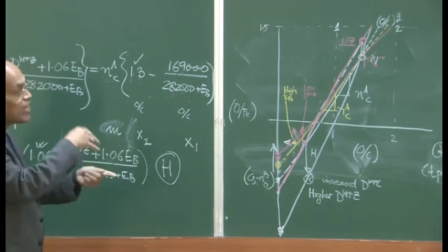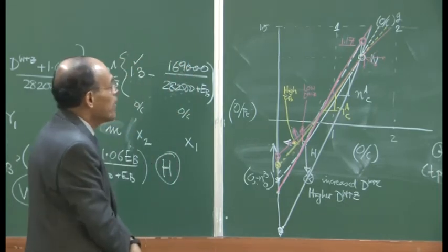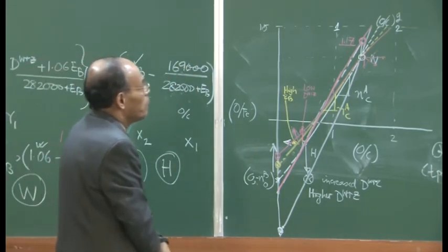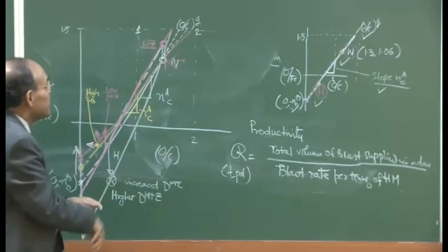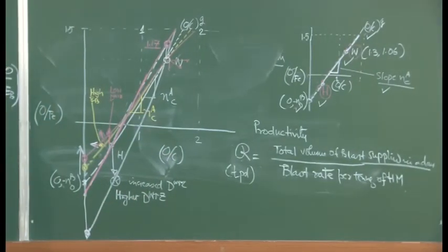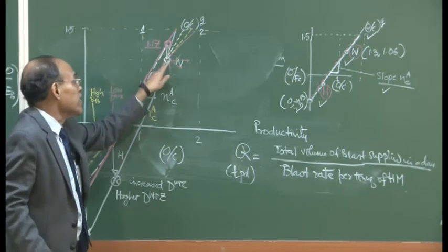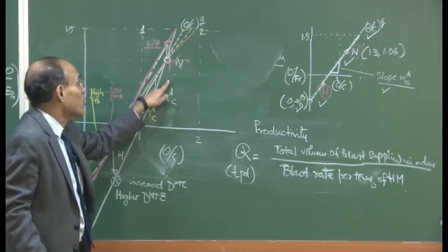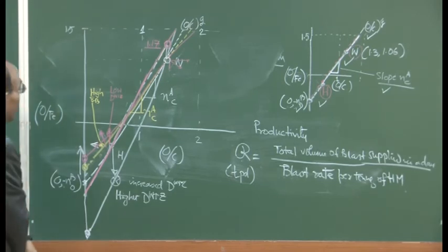Of course, internally this may get oxidized, but the moment I introduce the feed as Fe, I assume that Fe does not undergo oxidation and enters the reduction zone as Fe, which is of course debatable. But if you increase the proportion of Fe, the W point can go downwards, because that 1.06 will be less with metallic charges incorporated into the blast furnace burden material.